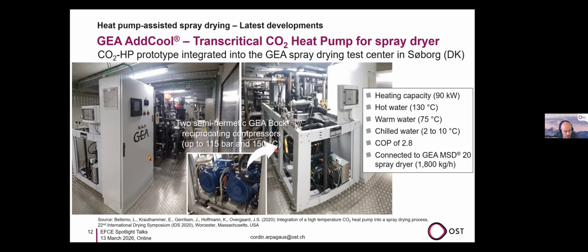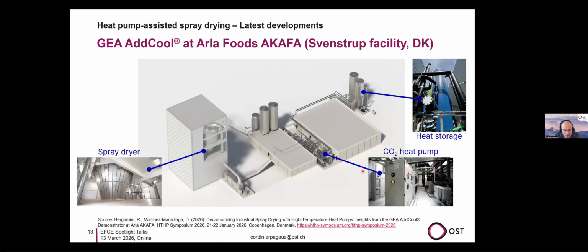And these are pictures of this heat pump that works with 2 piston compressors from GEA Bock with CO2, up to 115 bar, 150 degrees. It has a heating capacity of 90 kilowatts. So it's a pilot test setup, connected to a spray dryer, the GEA MSD 20, which has 1,800 kilograms per hour evaporation capacity. With this test facility, they improved their technology, and now they have a larger system at Arla Foods in Denmark as well, where they implemented this CO2 add-on technology at the dairy, the milk powder facility.